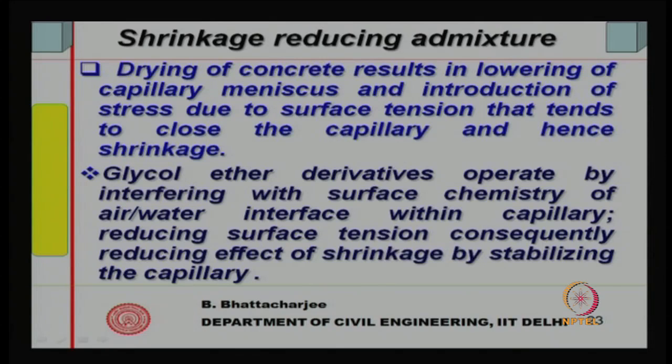Now, glycol and other derivatives, for example some glycol ether derivatives, operate by interfering with the surface chemistry of the air-water interface within the capillary, thus reducing the surface tension and consequently reducing the effect of shrinkage by stabilizing the capillary.